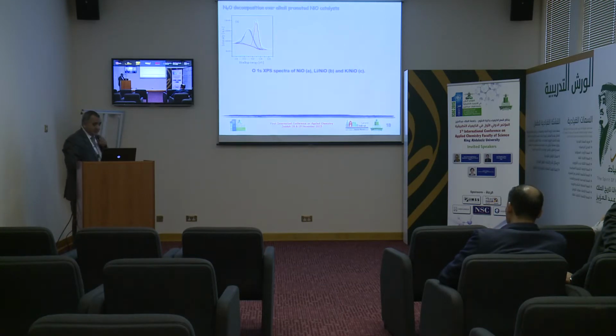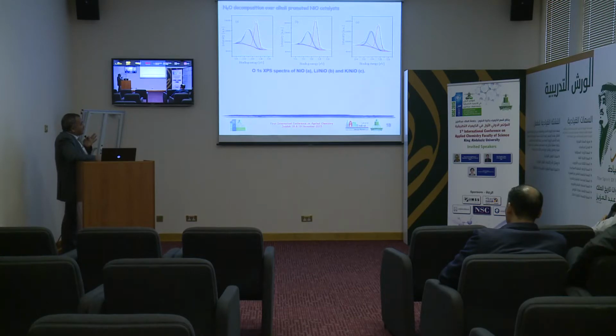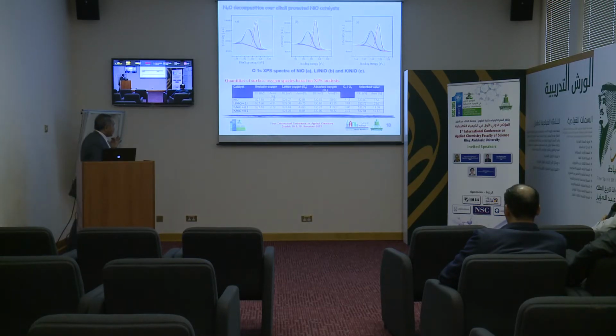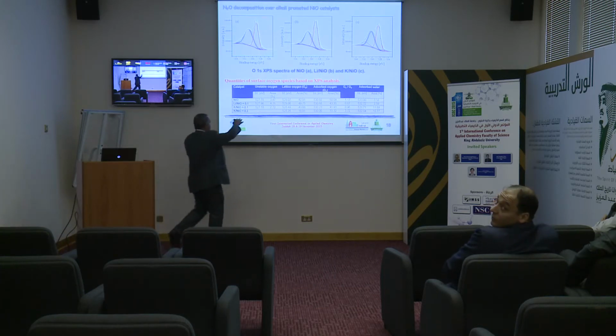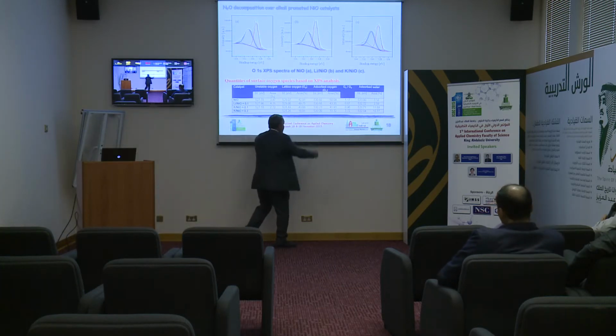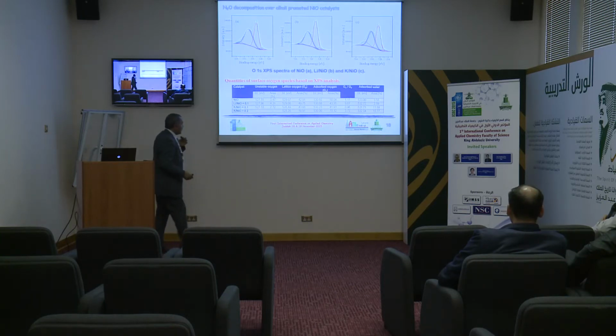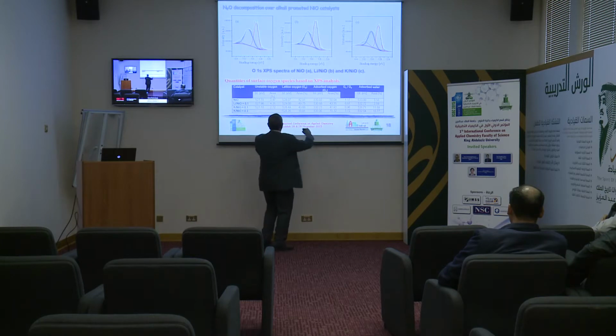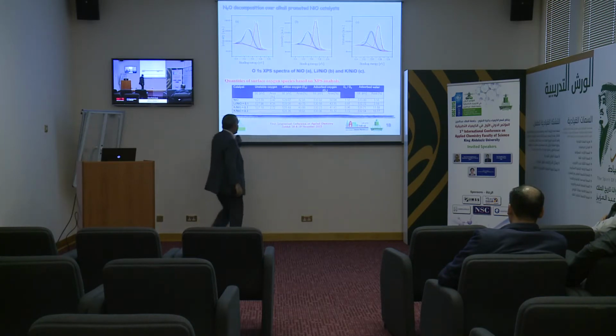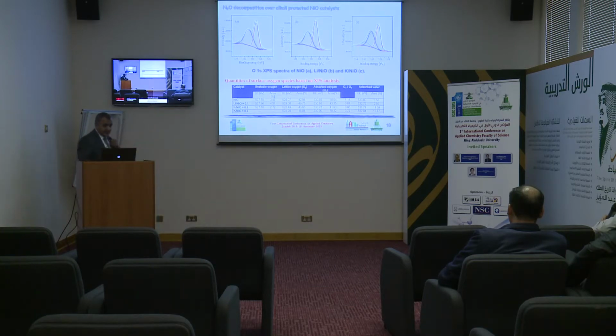Also we did the XPS for the O1s spectra. We can observe the presence of 4 peaks. These 4 peaks can be attributed to the presence of unstable oxygen, lattice oxygen, adsorbed oxygen, and adsorbed water. The most interesting thing is that the lattice oxygen binding energy also decreases upon adding the alkali dopant.